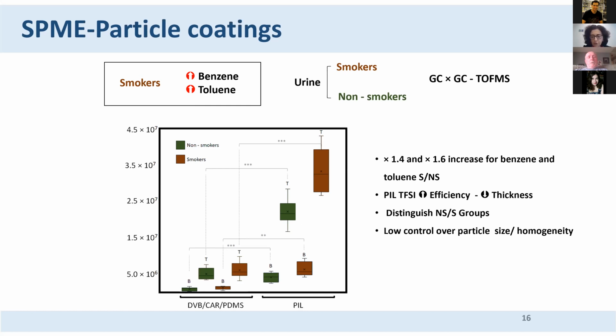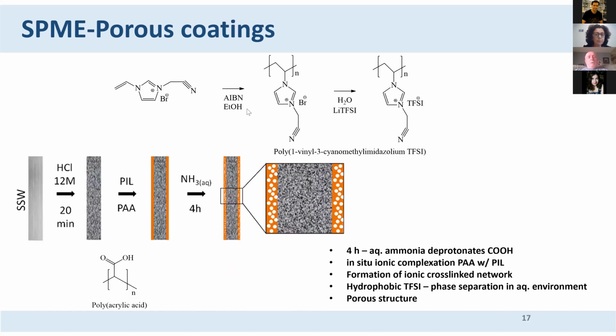Then we evolved to the porosity, the porous coatings. This work was done together with Ionic in the University of Stockholm in Sweden. So here what we did to create porosity, we really wanted to create porosity. And so we used a mixture of our polymeric ionic liquid, which is this one here. So it's a hydrophobic, it's a TFSI with TFSI counteranion with polyacrylic acid.